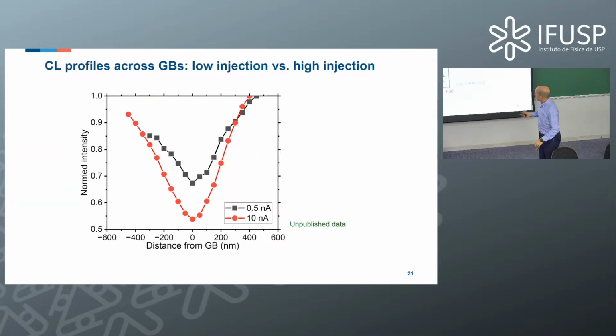You can see this. What we did is simply to vary the current for a specific material. This is a small current, yes. This is not a very strong decrease. But if you go to high current, then all of a sudden you have a much higher decrease, and so a much higher recombination velocity, which is not present if you operate a device in low injection conditions, which we normally do, right?